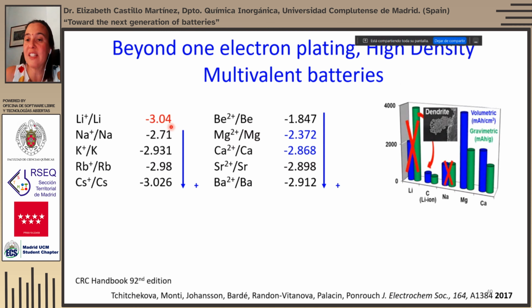So what is beyond lithium, beyond sodium and potassium ion? We have the multivalent chemistries. We've seen already they are all very abundant, and magnesium and calcium, specifically calcium, has a voltage of reaction which is very close to those of sodium and potassium. However, both of these chemistries, I mean, magnesium intercalation was investigated earlier, but calcium ion batteries has started to be explored more recently, and they do not have larger specific capacities, but actually because they can exchange 2 electrons or 3 in the case of aluminum, the volumetric energy densities are even higher than that of lithium-ion